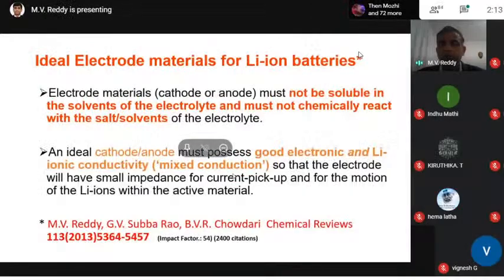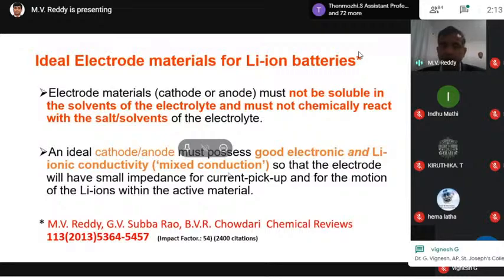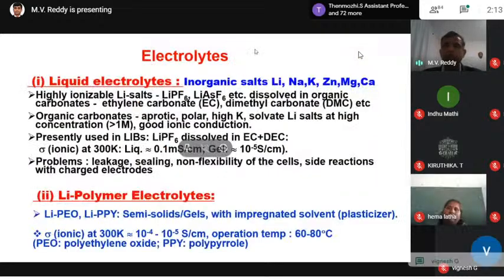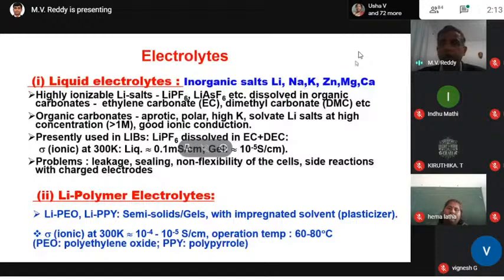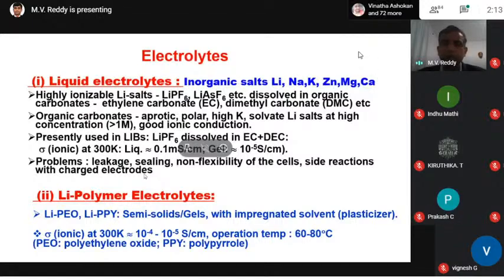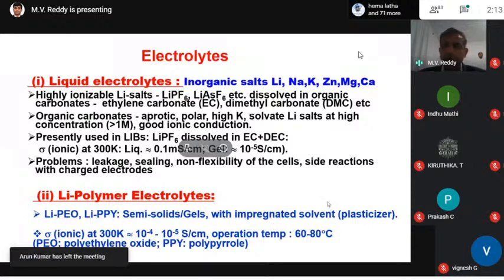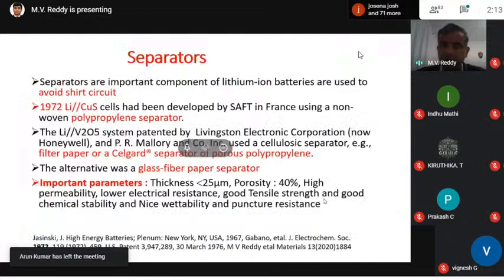Again, the material should be very stable, in the sense that the electrolyte won't react with either cathode or anode, and we have to look for mixed ion conductance. So conductivity is also very important. An insulator may not be really promising. Electrolytes are inorganic salts, either lithium or a different type of salt with different chemistry. Liquid electrolyte has good conductivity, but there is a flammability issue. That's why people have replaced liquid by polymer, or polymer with ionic liquid, or gel polymer electrolyte. Again, with polymer electrolyte, we need a somewhat higher temperature to get reasonable conductivity.